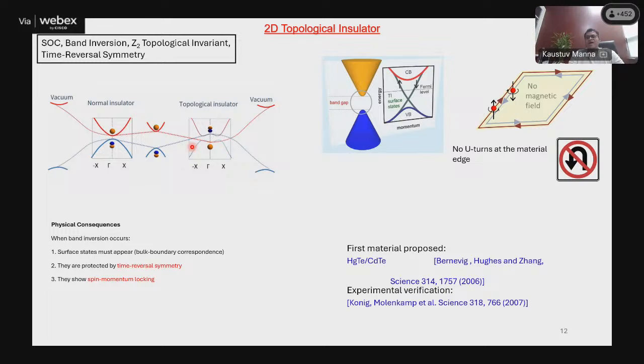at the edge of your material you have a crossing point, which is the edge state of your material. And because of this time reversal symmetry protection, because it's not broken, you must have two channels, one because of the down spin, another because of the up spin. So this is the schematic diagram, how it is presented. The bulk is already gapped out, and you have the surface state, which is the spin polarized surface state. This is how it is shown. The first prediction was done in 2006, just 20 years back, and then experimental verification was done just one year after that, in 2007 itself. So this is the 2D topological insulator.